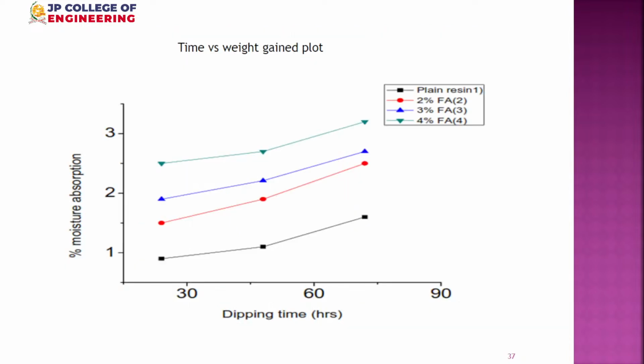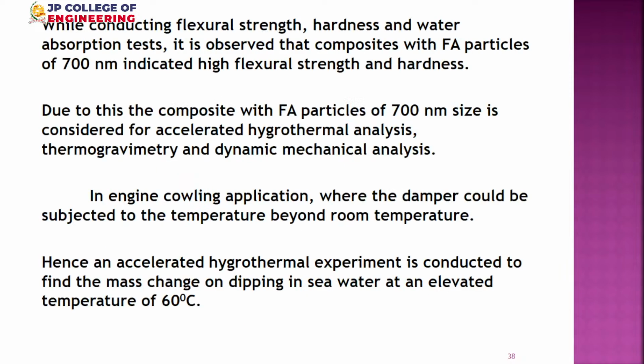So this shows that even in the initial time the water pickup is not high, but in the later period the gap also somewhat widened because of soaking of the particle, then the water enters in more, and therefore the water absorption increases. Next slide, please. Whatever it is, 1% to 2% is okay. So that is the thing. Therefore, around 700 nanometer size is somewhat okay, which gives minimal water absorption.